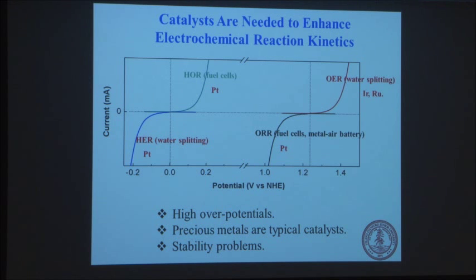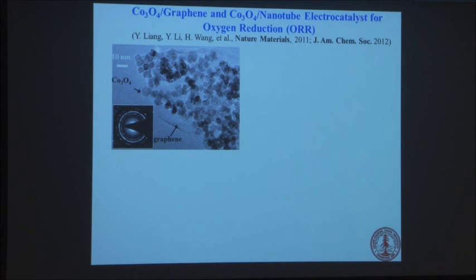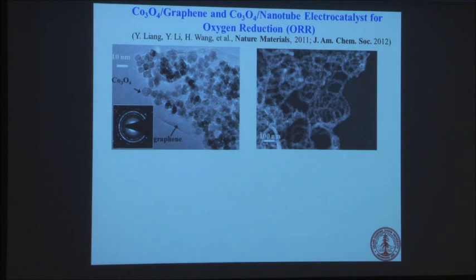So you need catalysts. A lot of precious metals are being used as catalysts, as a lot of you know, so you would like to have non-precious metal catalysts. And we found that this material, cobalt oxide on graphene, is a very good catalyst for oxygen reduction in alkaline solutions. Later, we made it on carbon nanotubes, and it turns out to be even better, because nanotubes are better conductors, and the interior of the tube is not damaged. So they can conduct electrons even better than the graphene that's damaged on the sheets.